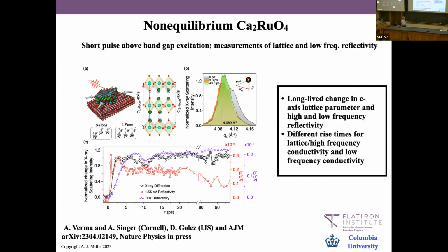It's going to appear here. Anyway, so you take this calcium ruthenate material, which I showed you before, in its lower temperature insulating state, and you irradiate it with a pulse of some amount at an energy which is high enough to excite carriers out of the ground state into the next excited state. Now, it's not shown here. I'll come to this on the next slide, but if you excite it weakly, nothing much happens.